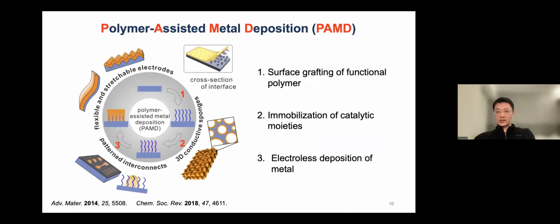Luckily, we've been working on a technology we call polymer-assisted metal deposition, PAMD for short, which allows us to deposit metal from the bottom up in a chemically reductive environment. We started this research about 13 years ago. What we did was first modify the surface with a thin layer of polymer, which is designed in a way that allows absorption of inorganic salts or nanoparticles, if you want. And these moieties are designed to assist the subsequent metal deposition. Of course, we can also do metal oxide deposition or other materials as well, but in this case, we do electroless deposition of metal.